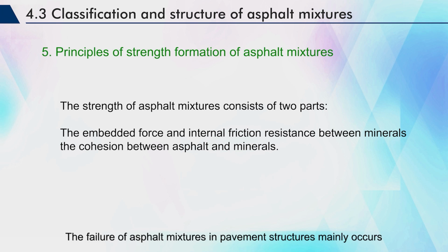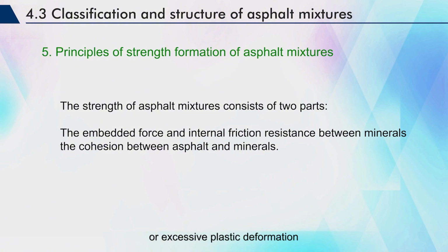The failure of asphalt mixtures in pavement structures mainly occurs at high temperatures due to insufficient shear strength or excessive plastic deformation, resulting in pushing and squeezing, as well as at low temperatures due to insufficient tensile strength or poor deformation ability, resulting in cracking.